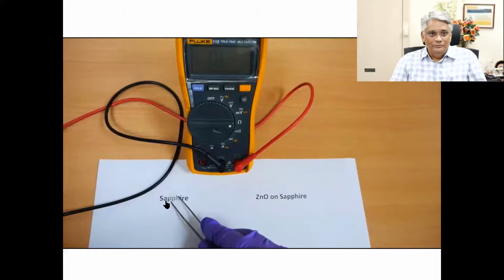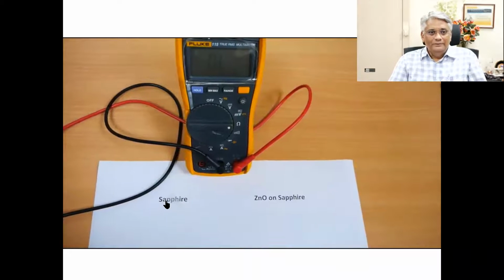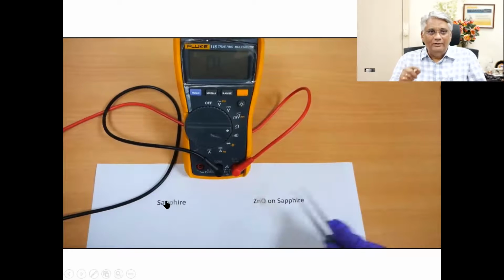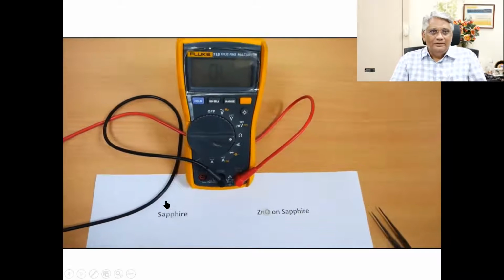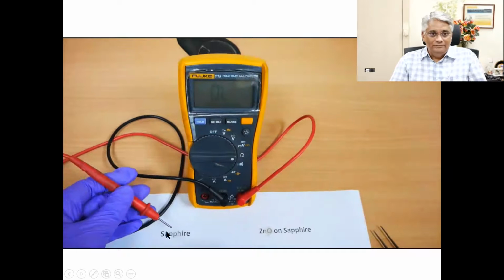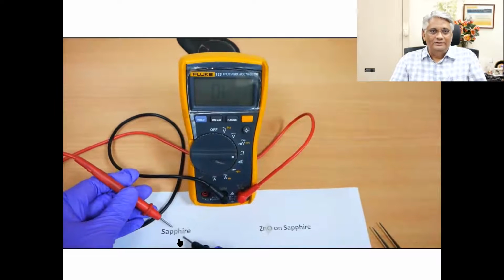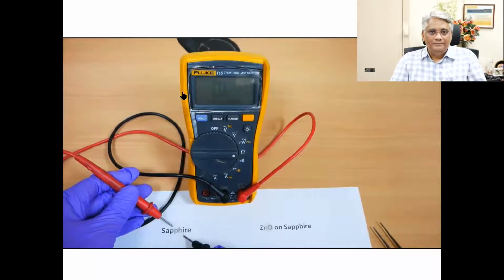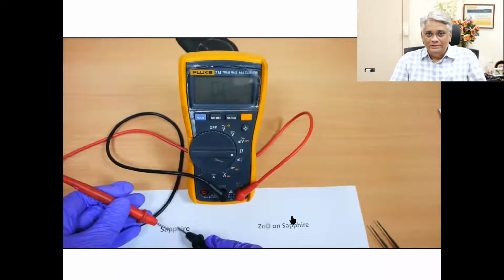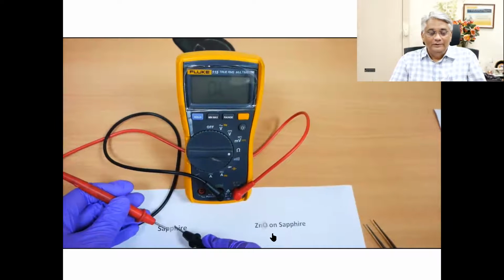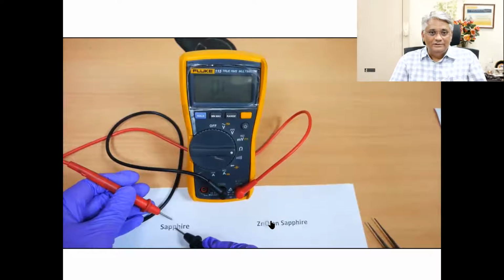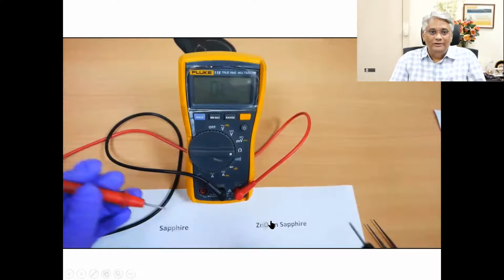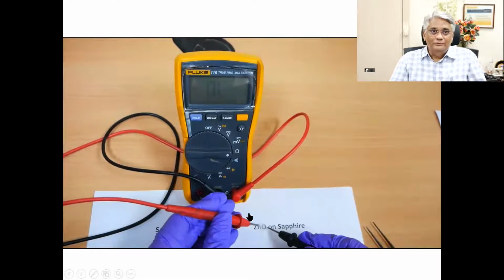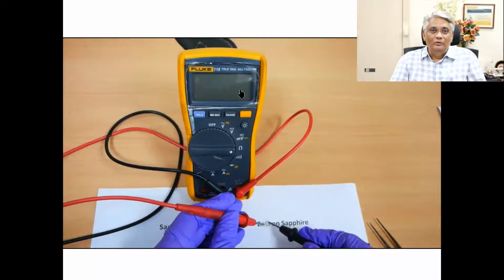Then sapphire, which is also transparent. This I told you in the last class. Alumina, alpha alumina is sapphire. But sapphire is an insulator because alumina is an insulator. So overload there. Okay. Now this is zinc oxide on sapphire. This is still not doped zinc oxide. Zinc oxide just with oxygen vacancies. That itself shows conductivity in few kilo ohms.